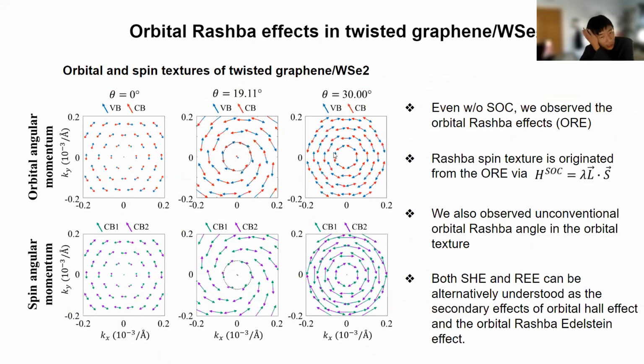Before we look at the transport, it's very instructive to first look at the spin texture. Let's just focus on the spin texture and ignore the orbital texture for now. For the spin texture, you see that the spin has this locking with the momentum, very similar to what we see in Rashba split bands. But an interesting thing that we observe here is that the spin is not perfectly locked at 90 degrees. There is this canting of the spin away from 90 degrees. That is something interesting, and what we're going to show is that it produces some Rashba-Edelstein effect that is unconventional because of this canting of the spin.